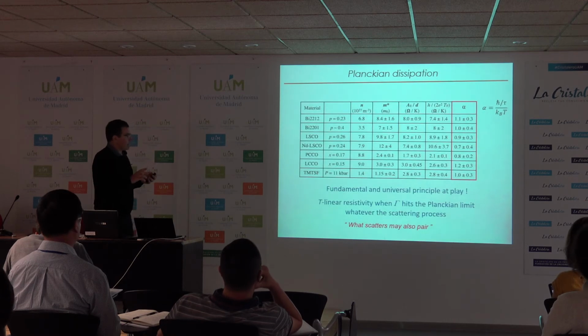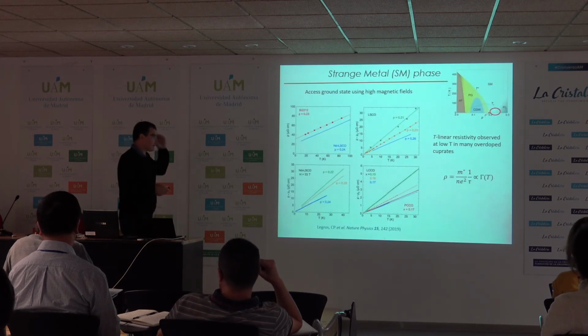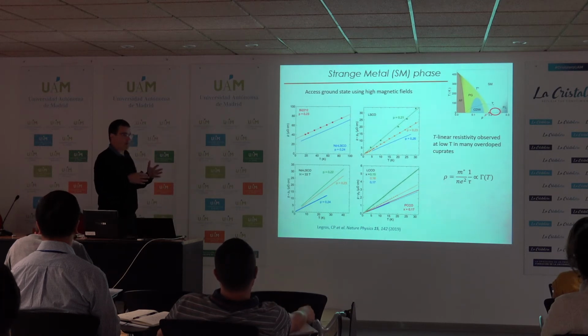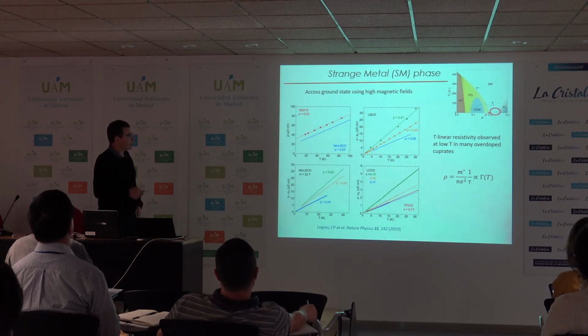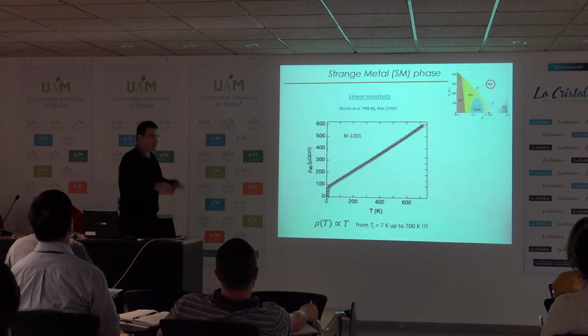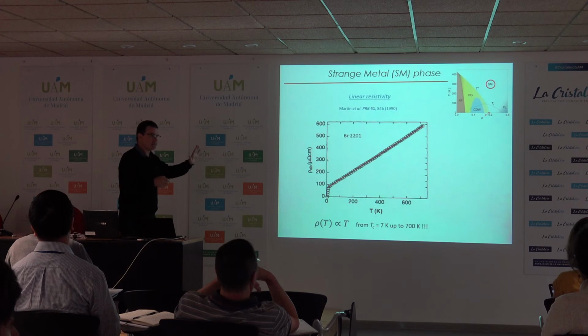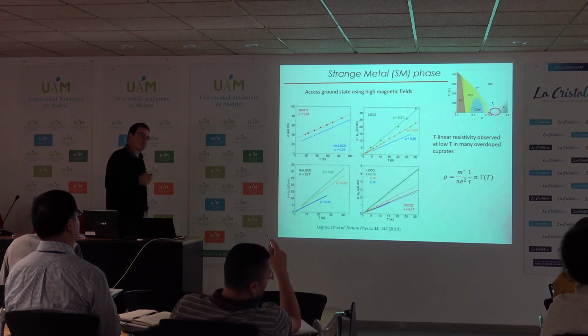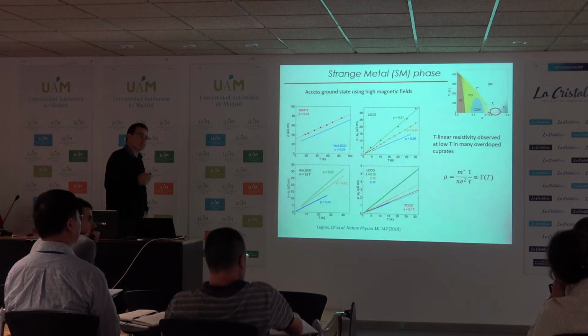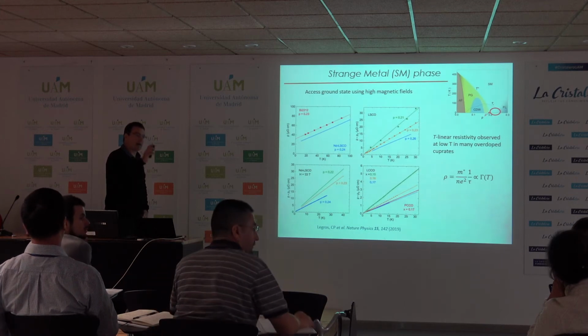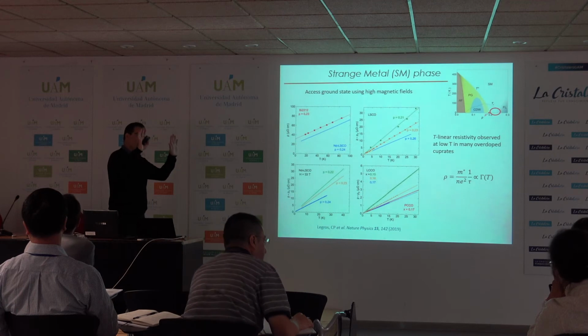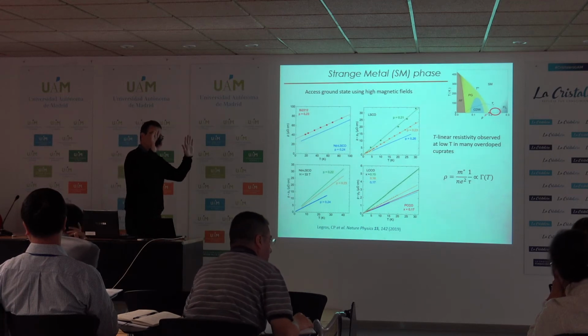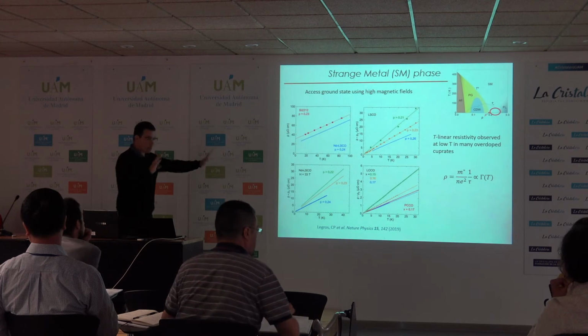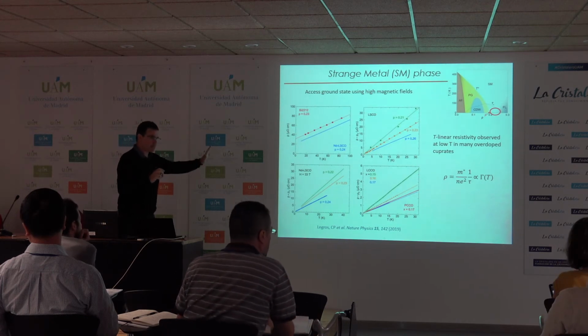Okay, so I was a bit quick on this part. What you have to notice is that we already concentrate on the low temperature part, on the slope of the resistivity at low temperature. For this compound, I show this at the beginning because this is really the hallmark of... Perfectly okay. But if I take it literally, we do know that these systems surpass the sheet resistance h over e squared at high temperature. But the incoherent bad metal regime that we have at high temperature is not the one that I'm discussing here at low temperature.